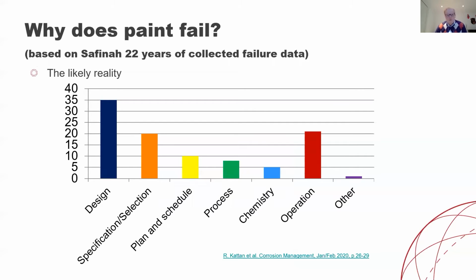And if you look at why does paint in general fail, this is the likely reality. This is based on Safinah's 22 years of collected failure data. It might be surprising to you, but actually the biggest failure is design. Edges and corners and so on haven't been rounded, so you get a lot of corrosion in those areas. The second biggest reason for paint failure is failure during operation, and then third is specification and selection of the coating. So it's very important to select the right coating to give the protection under the operational and climatic conditions you're operating. It might also be very surprising to you that process, which is surface pretreatment and paint application, has less impact when it comes to paint failures. It's about 7%.